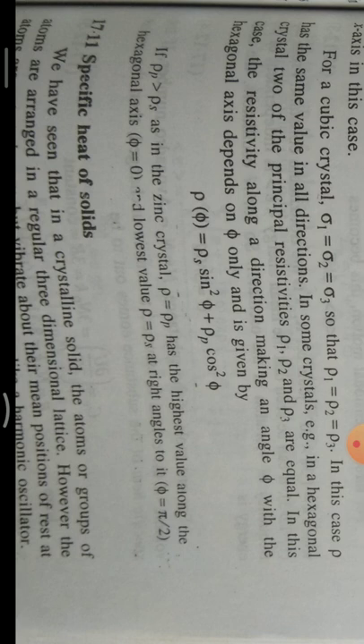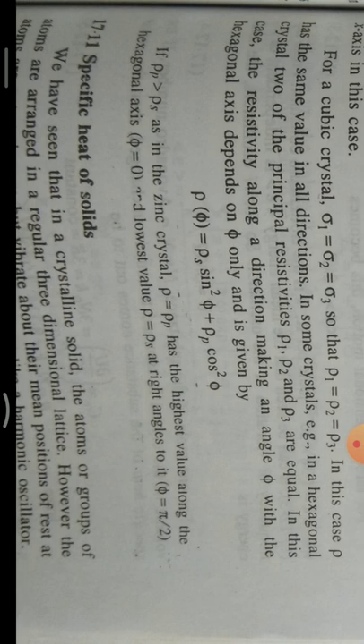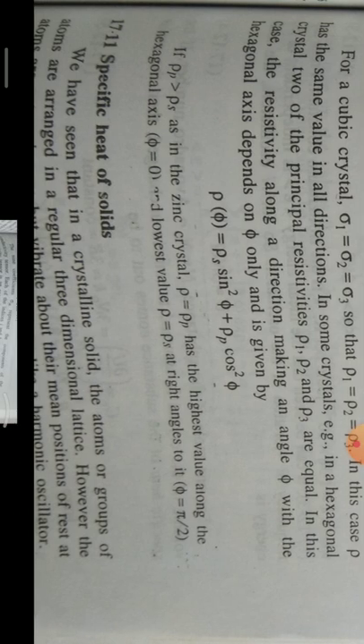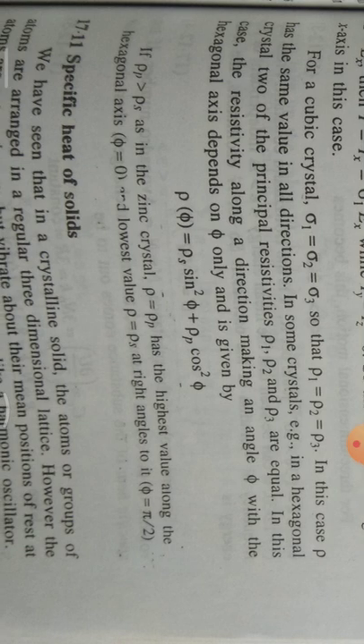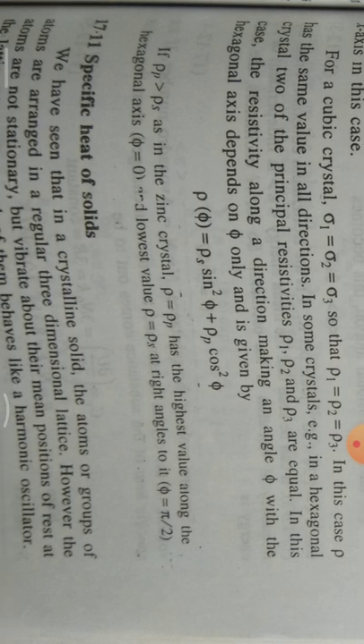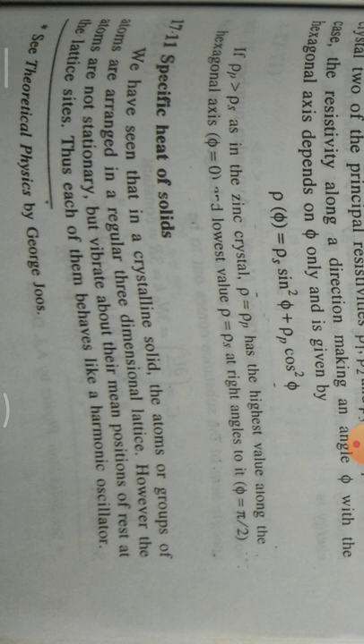In this case, the resistivity along a direction making an angle phi with the hexagonal axis depends on phi only and is given by rho phi is equal to rho s sine square phi plus rho p cosine square phi, if rho p is greater than rho s. As in zinc crystals, rho is equal to rho p has the highest value along the hexagonal axis, phi is equal to 0, and the lowest value rho s is at right angle to it, phi is equal to pi by 2.